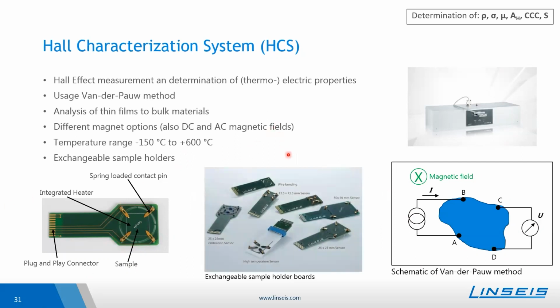The Hall characterization system has different exchangeable sample holder boards for different sized samples, also for the Seebeck coefficient determination. There's also a high temperature sensor with which one can heat up to 600 degrees Celsius. The classical boards can go up to about 200 degrees Celsius. The Hall characterization system can be equipped with different magnet options, like a permanent magnet, electromagnet, or a Halbach magnet.